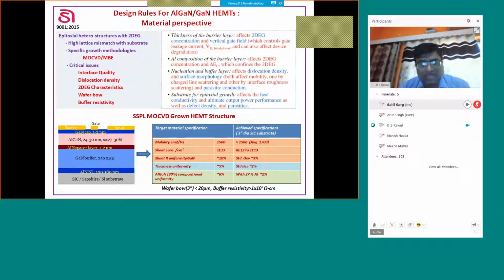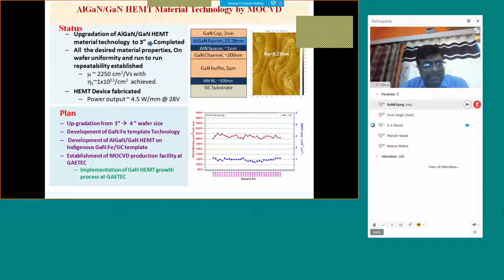we have our own material growth system optimized to deliver continuous high mobility of more than 2000 centimeter square per volt per second with an Ns of 1 to 1.5 E13. And the bow of the wafers of 3-inch size, we have controlled to less than 20 micron, which is as good as available in the commercial market. And the present status of growth is that we have a 3-inch growth technology, and our indigenous material has delivered devices with 4 watt per mm at 28 volt up to C band,